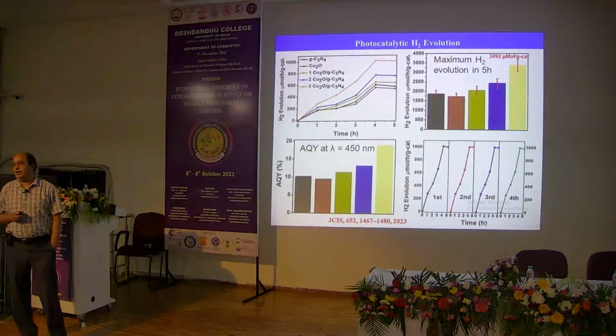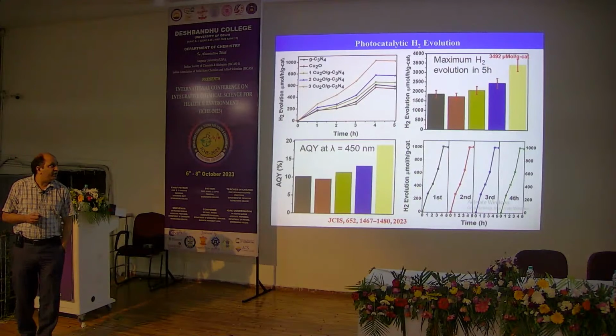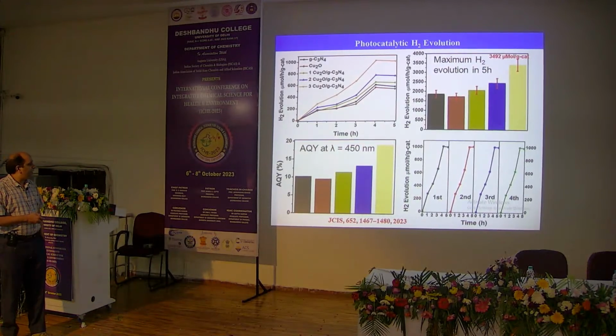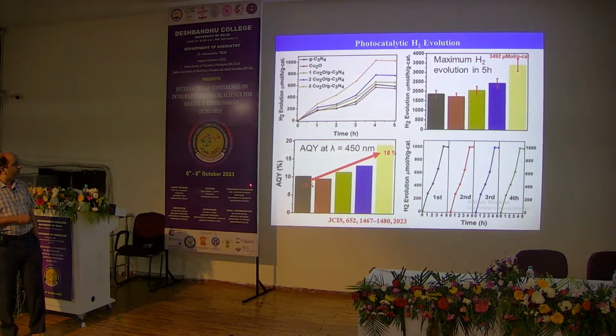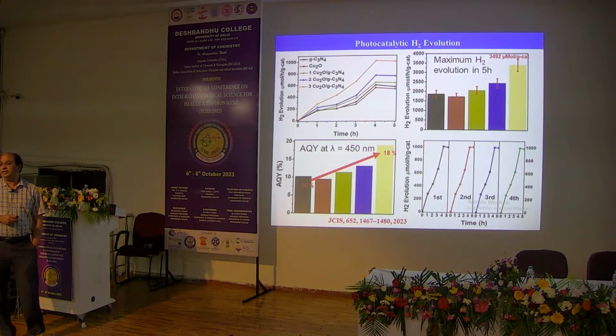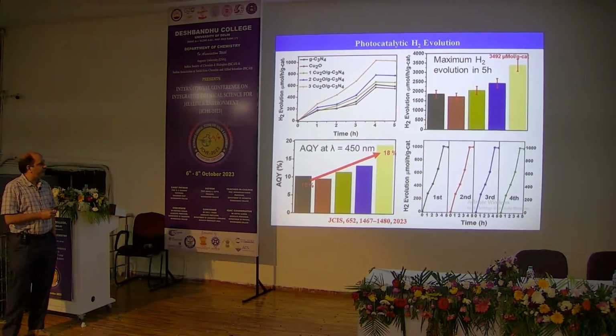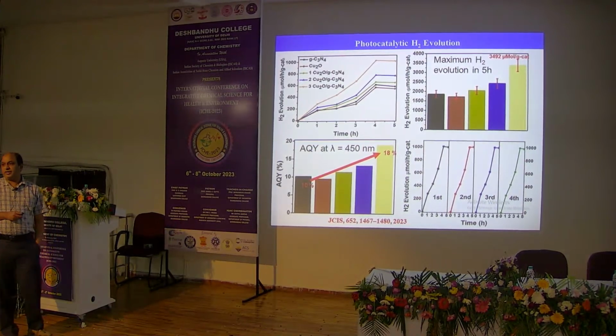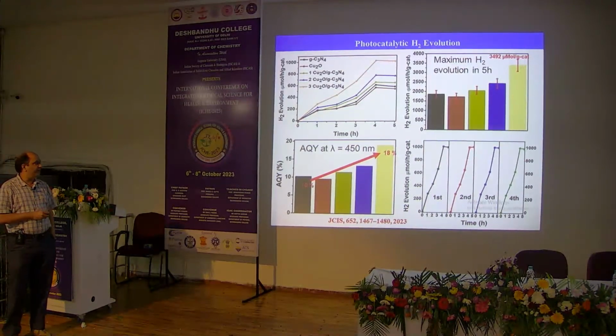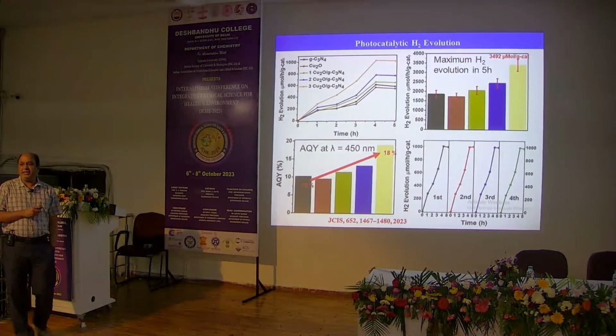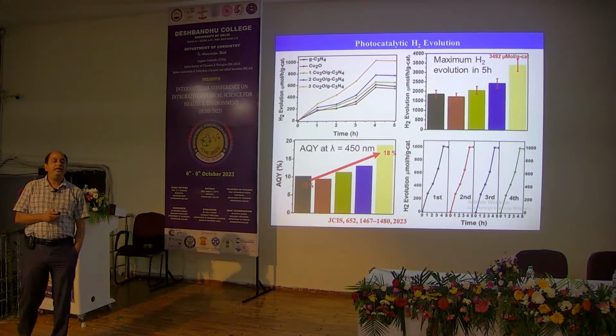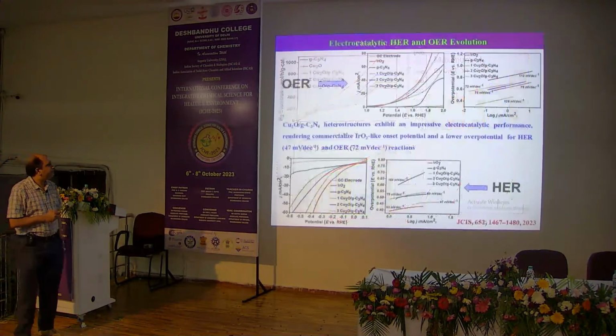3.5 millimole per gram per hour of hydrogen, and the apparent quantum yield is increased from 10 to 18% for the 30% copper oxide over graphitic carbon nitride. So this is the first report which reports the highest apparent quantum yield for this binary heterostructure, meaning copper oxide and graphitic carbon nitride.